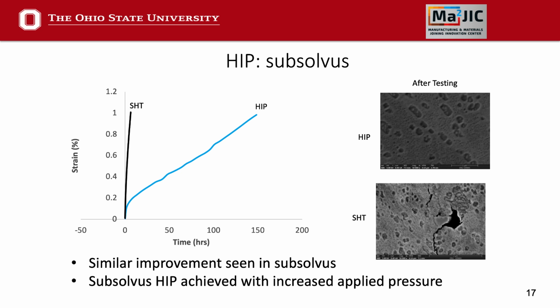We kind of seem to see that the main reason for that is during testing of the solutionized material, we get grain boundary decohesion and a large amount of cracking, and this seems to be fixed through using HIP. We don't see this large amount of cracking during testing, which is having a huge impact on our mechanical behavior. Very interesting. So what's the significance of these findings?